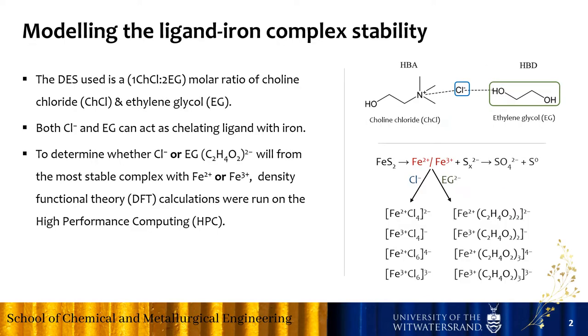So what is DES? DES is a combination of two components: one acts as a hydrogen bond acceptor and the other acts as a hydrogen bond donor. After mixing these two components together, they develop a hydrogen bond network and meet at a eutectic point, which has a lower melting point than both individual components.